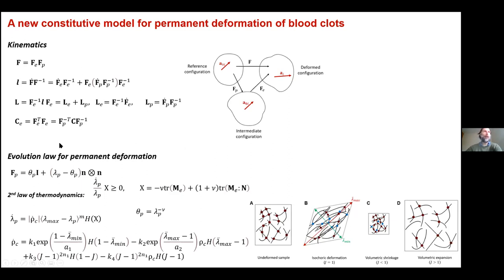that the plasticity in the blood clot is a result of the formation of new bonds between fibers in the fiber network. And as we deform the material, these strands of fibrin come closer together if we do a compaction, and these will form new bonds, which will, in a sense, give us a permanent deformation. When we then unload the material, these new bonds stay intact, and the network doesn't spring back to its original position.